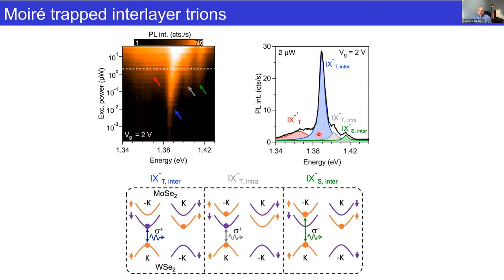But we can assign these other three peaks to being negative trions, with either an intervalley configuration, where basically the extra electron is in the other valley, or in the same valley, as you see here for the gray peak. Or we can have the singlet state rather than the triplet state, where we have the trion, the extra carrier in the other valley, and we have the spin singlet transition. And again, we can confirm this with magneto-optics by looking at the g-factor.